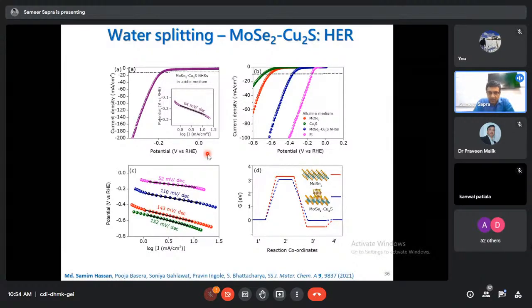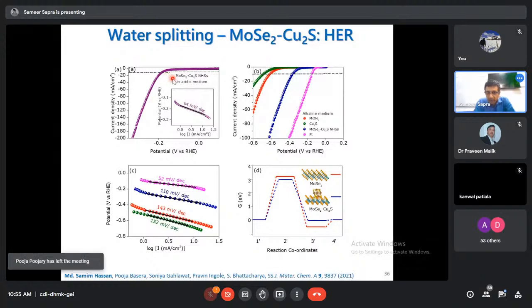So under alkaline conditions, can we do hydrogen evolution? Yes. This was hydrogen evolution, roughly about 190 millivolts overpotential for the heterostructure, molybdenum selenide cuprous sulfide, under acidic conditions. But in alkaline conditions, the overpotentials are slightly higher, roughly about 400 millivolts, but then there's a separate mechanism. Still, the good thing is that you do have hydrogen evolution under alkaline conditions, and therefore you can use this for water splitting from the same pot. Okay, you can have both hydrogen and oxygen coming out from the same material under the same conditions.